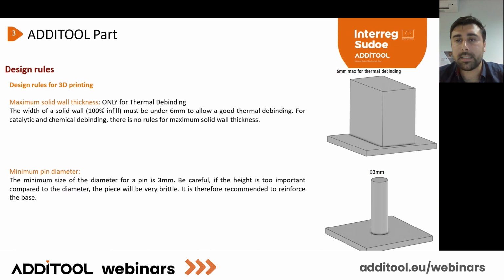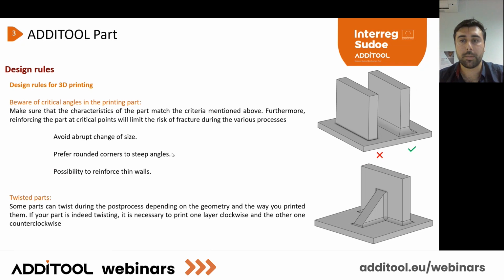Maximum solid wall thickness: this rule is very important, but it is only for processes that require only thermal debinding. It is not possible to thermally debind a big wall of about 20 millimeters thickness, because you will not debind from the core to the periphery. You will have a lot of deformation, a lot of collapse, etc. So it is important to not go past 5 or 6 millimeters for thermal debinding. If you do a catalytic or solvent debinding before, you have no limitation on the wall size. And 3 millimeters for the pin diameter, just for information.